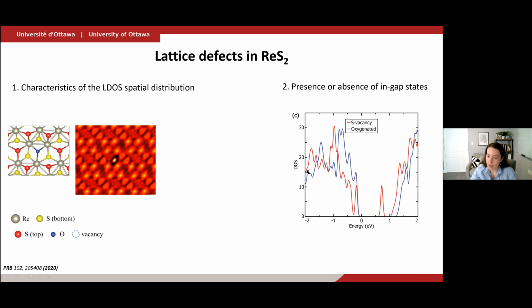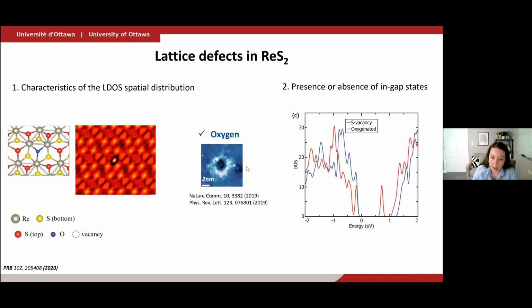And moreover, if it were just the sulfur vacancy, it would have an electronic state somewhere in the semiconducting gap. If it has an oxygen passivating that defect, it would not have an electronic state in the gap. And so going by these two pieces of information and comparing them to our experiment, we find that very likely oxygen is responsible for these atomic scale defects. And that is adding up to a wealth of experimental results also coming out from other groups on transition metal dichalcogenides.